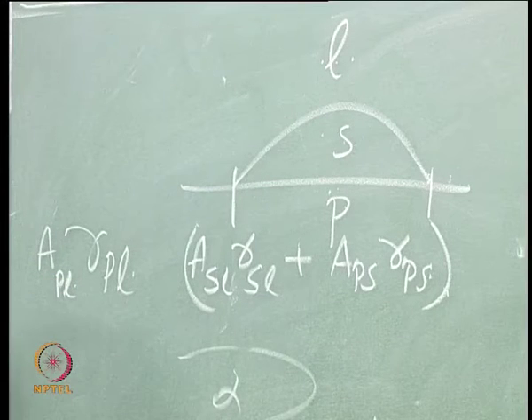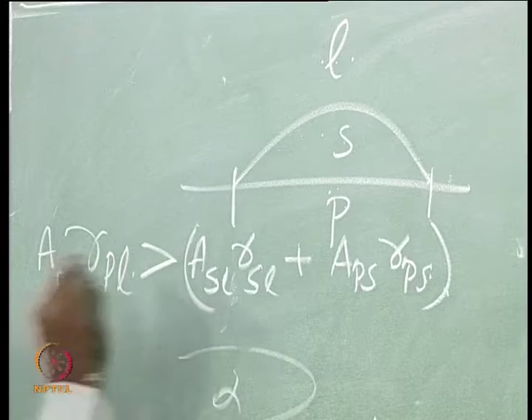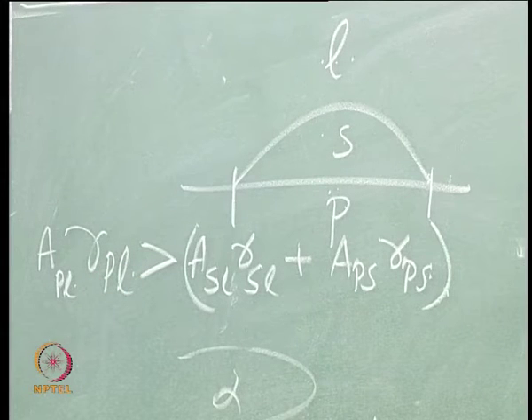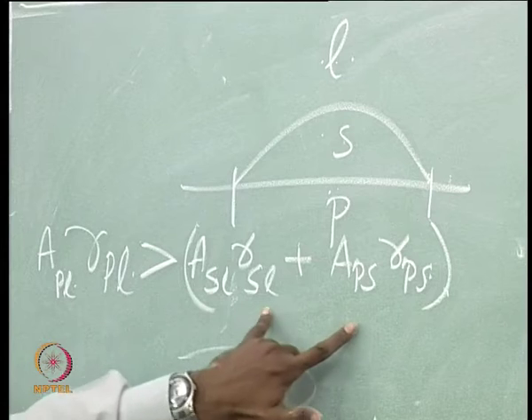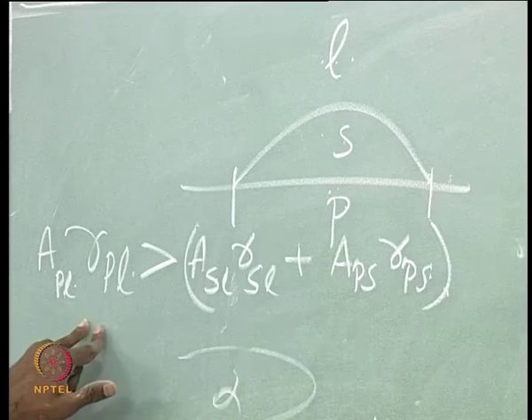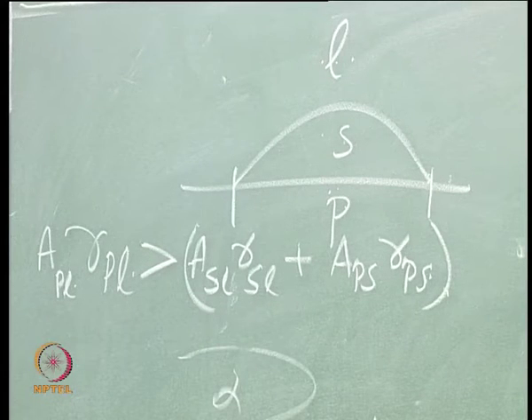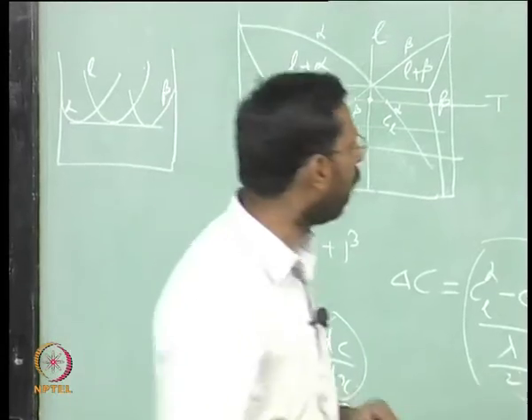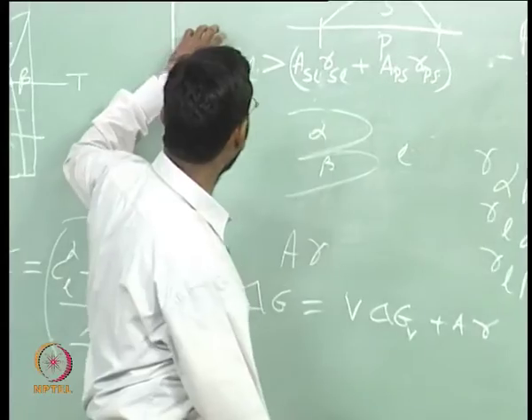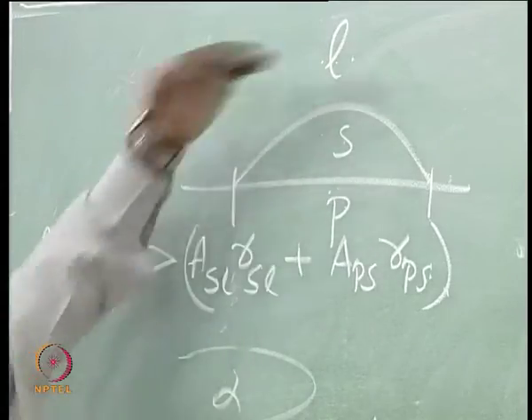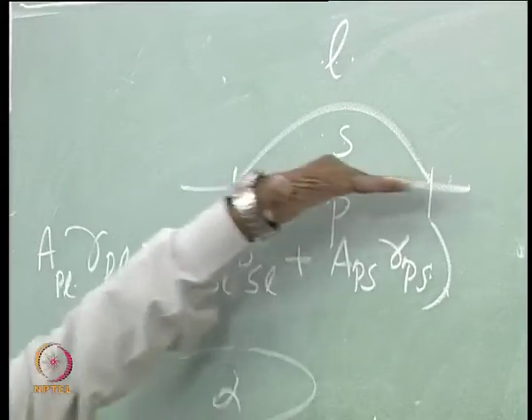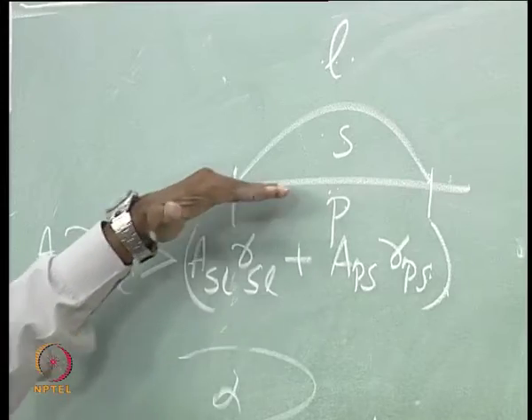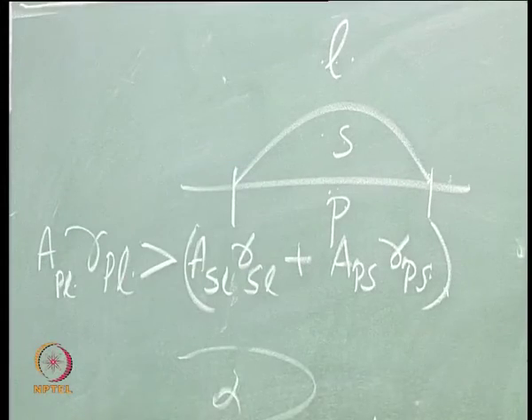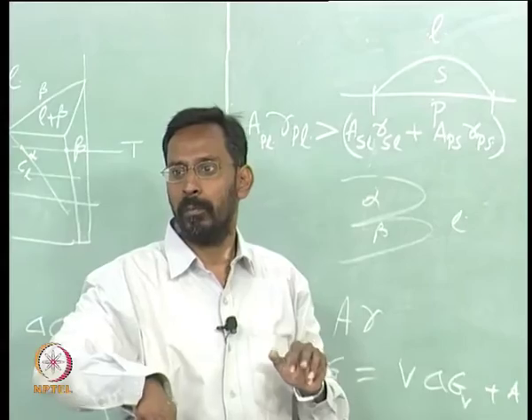These two are replacing A of PL into gamma of PL. If this combination is smaller than the original, then only the heterogeneous nucleation will take place, because this interface is replaced with two interfaces: a particle-liquid interface and particle-solid interface.